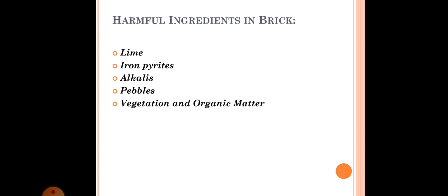But if lime is present in excess, it will cause the brick to melt and the brick will start losing its shape. And also if lime is present in the form of lumps, it will be converted into quick lime after it is burnt, and this will again lead to expansion and cause splitting of the bricks into pieces. So lime is not desirable in excess.